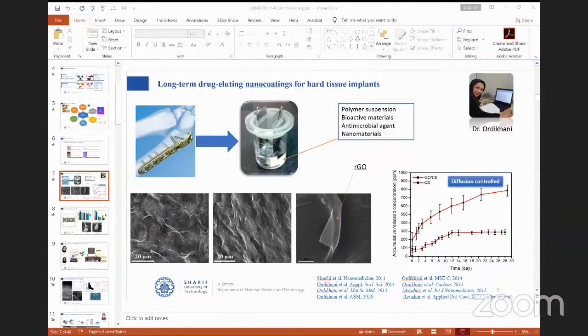We used, for example, chitosan embedded with bioactive glass particles, and tried to incorporate vancomycin or other biomolecules inside the polymer matrix and to control the release of the drug. However, the problem is we could not control the drug release rate. To do so, we also incorporated reduced graphene oxide inside the polymeric matrix and conjugated the drug to the nanomaterials by surface functional groups.